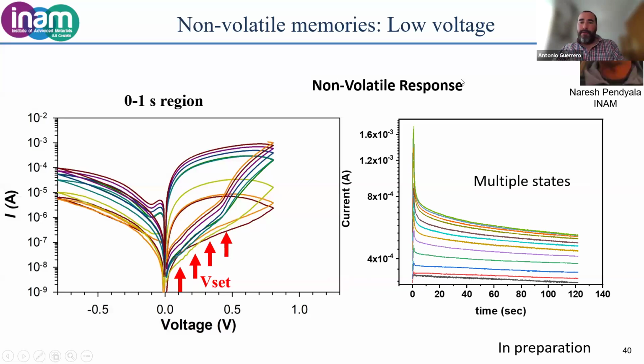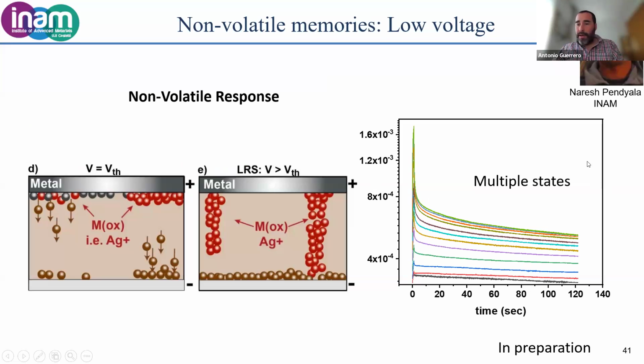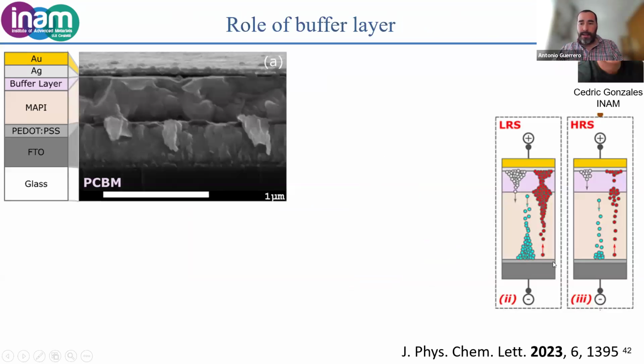We can also make non-volatile response using different configurations, but I don't think I will have time to show that. We can also reach multiple states with different perovskite formulations and different external contacts, but I don't have time to describe that. I just want to show you as well that the buffer layer plays a very important role, because in the end, the ions coming from the perovskite need to go through these thin layers, which are typically in the order of nanometers. So they can also form conductive filaments across the buffer layers.